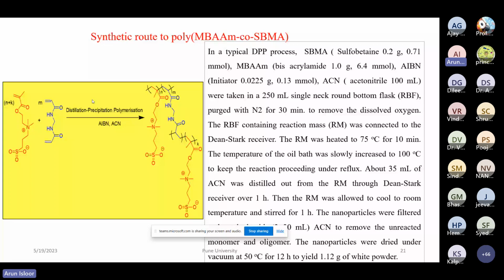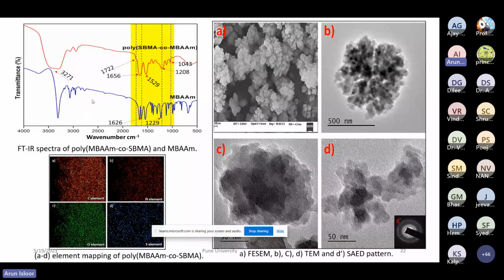It was allowed to cool to room temperature, and then the nanoparticles were filtered and dried. So this is how we prepared the zwitterionic polymer nanoparticles. And then of course all the required characterization was done, such as FTIR and elemental mapping, which, as you can see here, showed the presence of carbon, nitrogen, oxygen, as well as sulfur, and they were also characterized with FESEM and TEM.